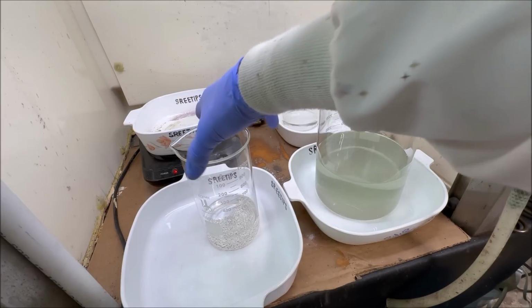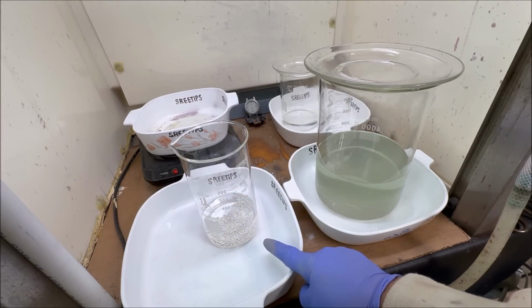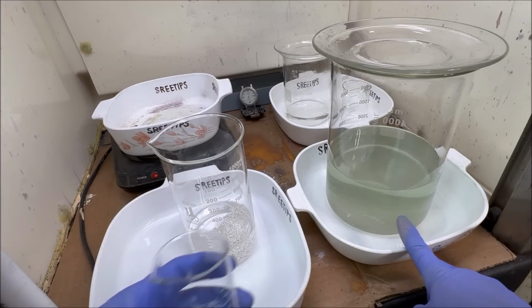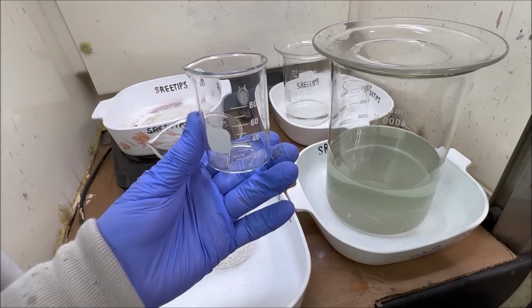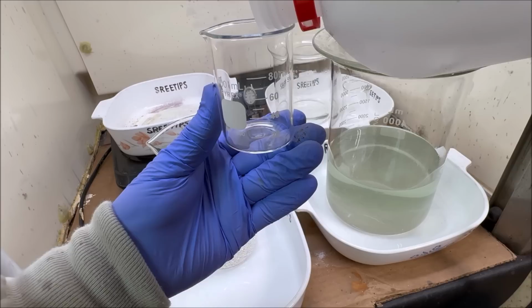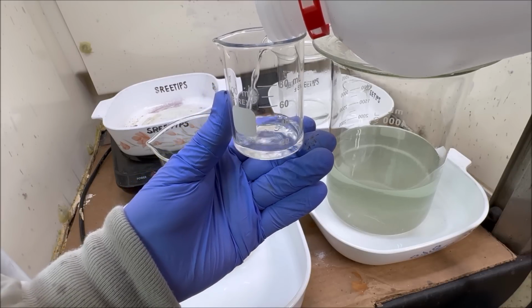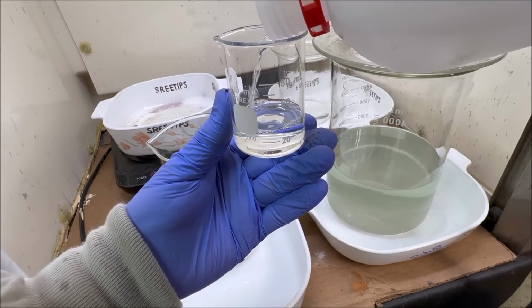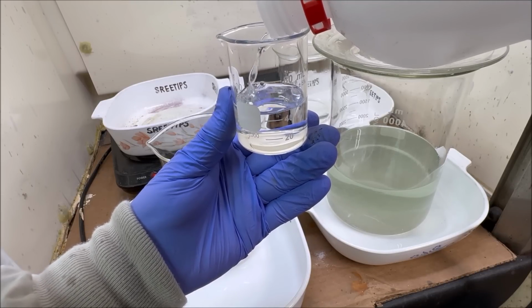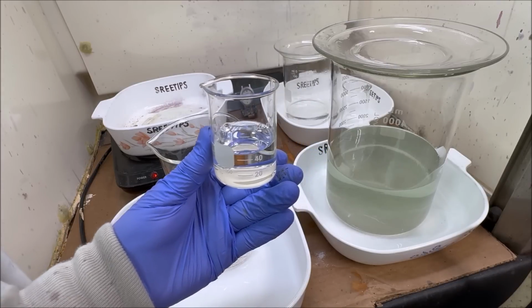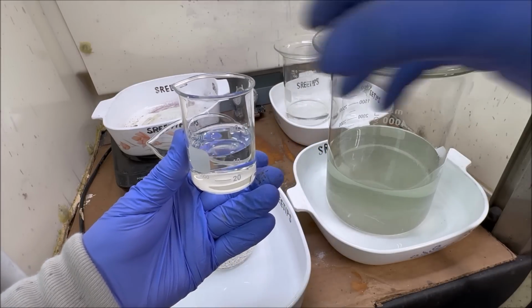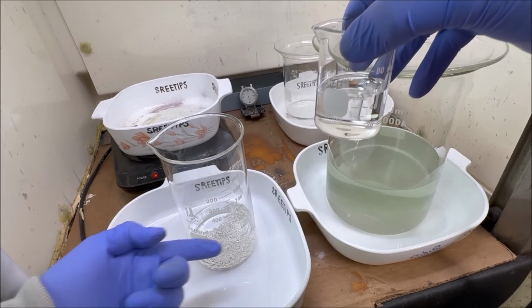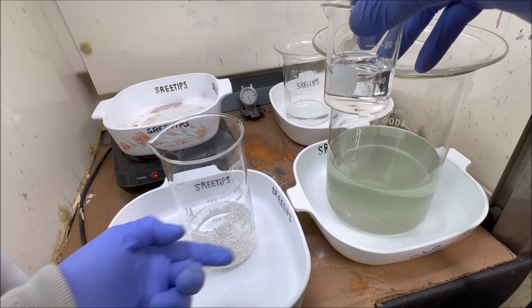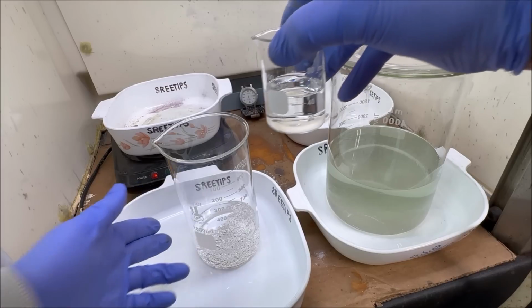I've added 100 milliliters of distilled water to about 90 grams of some of the pure silver crystal from my electrolytic silver cell. A little bit of copper in the electrolyte doesn't matter. In fact, there's one refiner on the gold refining forum, Gold Silver Pro, and he claims that a little bit of copper in the electrolyte is beneficial for the crystal growth in the silver cell. But since I used some of my crystal to make the electrolyte, now I got to prove that it ain't my crystal that's got copper in it.